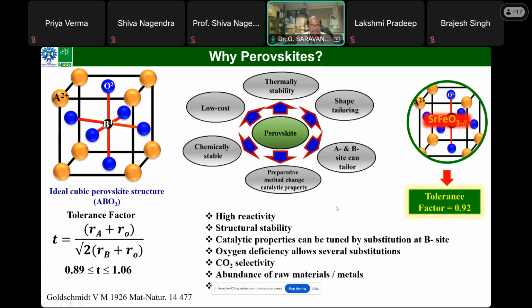So we selected perovskite catalyst. Actually, perovskite-based catalysts people have been using for quite some time back. Because of the presence of lead and sulfur in the gasoline, the stability of this catalyst became questionable. So people haven't used it except for R&D or research purposes. But because of the improvement in sulfur as well as lead in gasoline, there is renewed interest